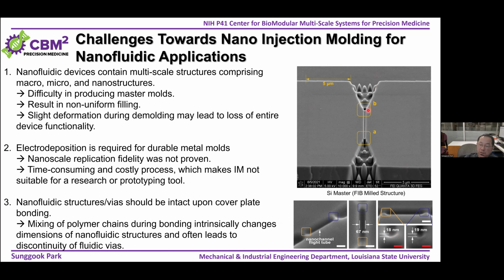But what you can realize is it is not really a periodic structure. It contains a multi-scale structure, including nanoscale and microscale, and also macroscale for the inlet and outlet of the analytes. So some challenges in developing this nano injection molding include, for example, that it's difficult to produce master molds with high quality. And if you use those multi-scale structures for molding, that can result in non-uniform filling. And if you have a slight deformation during demolding, I think the microstructures won't be affected so much, but the nanostructures will lose the entire device functionality.